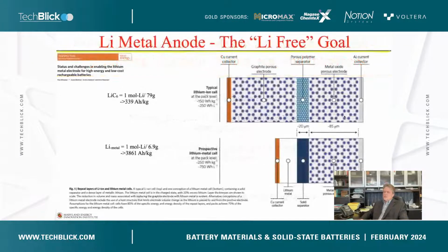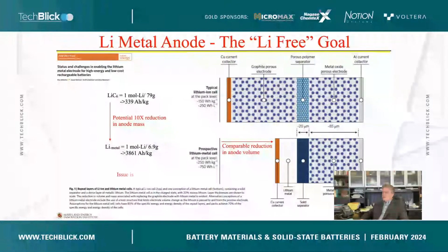Okay. So there's been a big focus on trying to get to a lithium free lithium metal anode. Obviously, there's the reduction in mass from a carbon anode to lithium metal, but also a comparable reduction in anode volume if you can go lithium free. The issue is, how do you deal with the infinite volume expansion upon every cycle? That's been a major issue for lithium metal batteries, which are trying to be lithium free in that the lithium comes from the cathode and not from the anode itself.